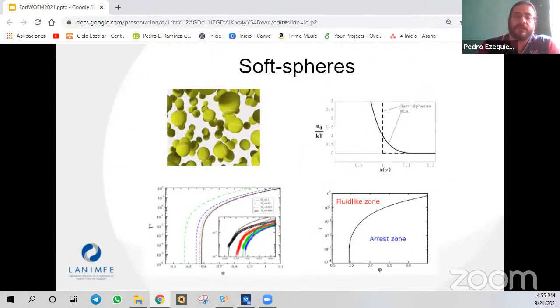In order to show the predictions of the NE-SCGLE, we choose a simple model of a fluid, a soft sphere model described by a truncated Lennard-Jones potential, for which our calculation of local mobility at equilibrium coincides very well with computer simulations. And actually, we can determine the region for which the mobility becomes zero, which is the green line in the last picture on the screen. Below this line, the fluid is arrested and forms a solid-like state. Then we can study the relaxation process outside and inside the arrest region.